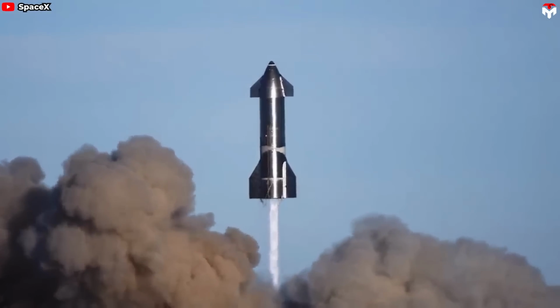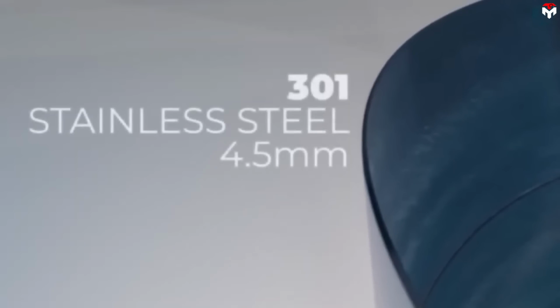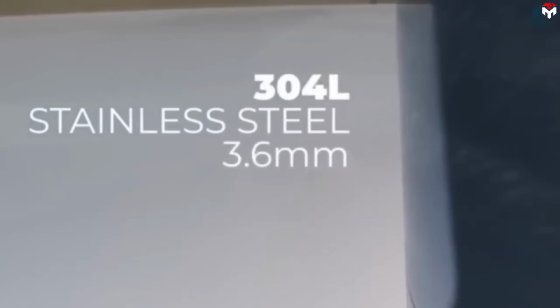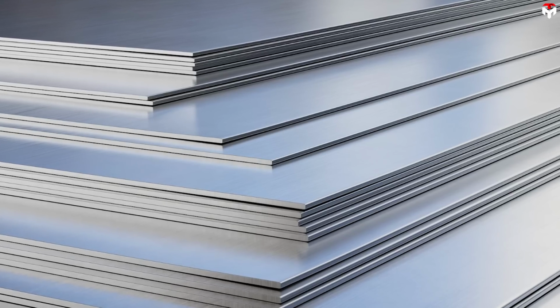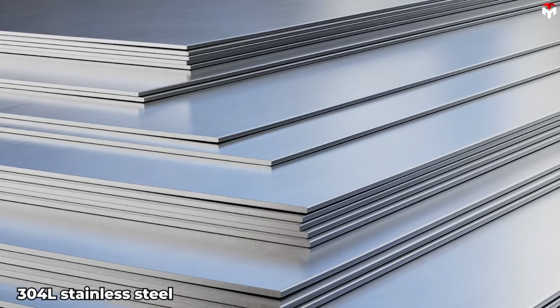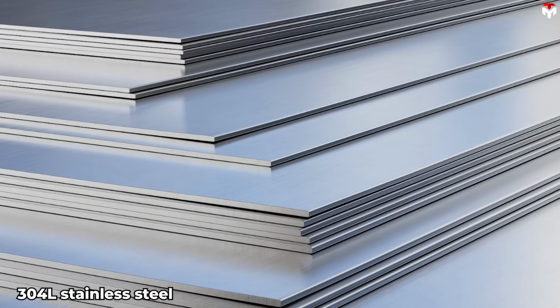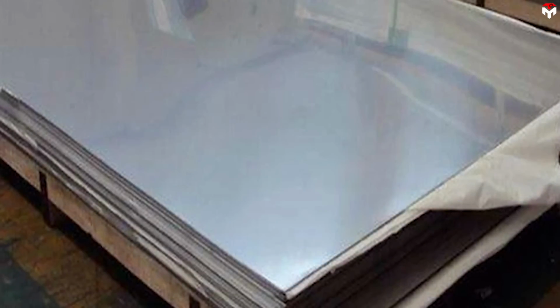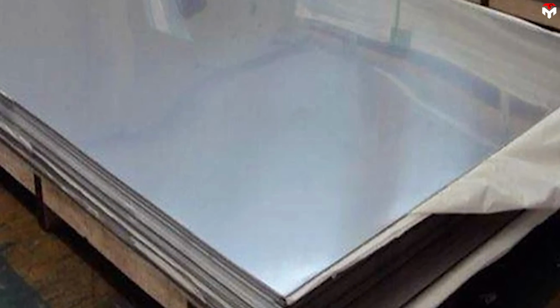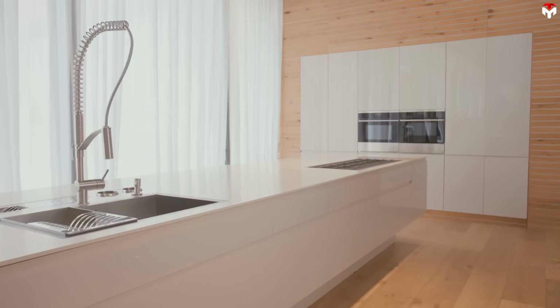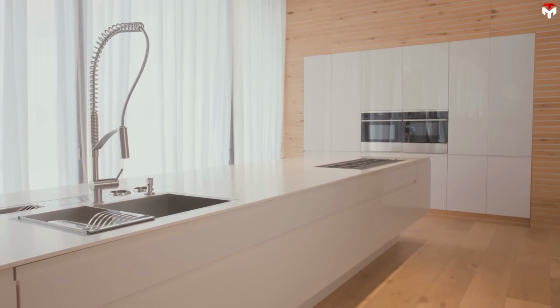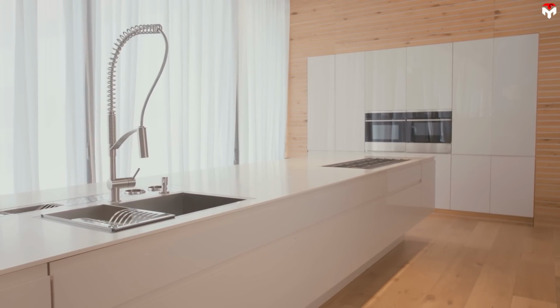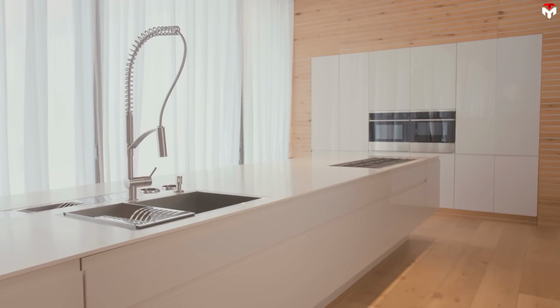From prototype SN8, SpaceX switched from stainless steel 301 to 304L stainless steel. Both are stainless steel, but this is a significant switch. 304L also has high chromium and nickel content. Chromium and nickel provide good corrosion resistance, hence it is one of the most commonly used steels in the world. 301 is used for springs and coils. 304 has higher chromium and less carbon, making it more corrosion resistant, which is why it's used for kitchen equipment